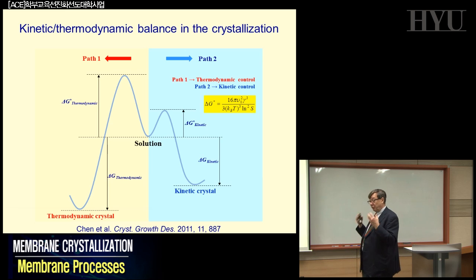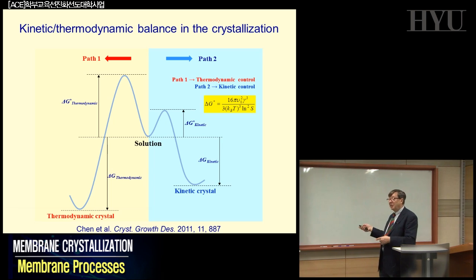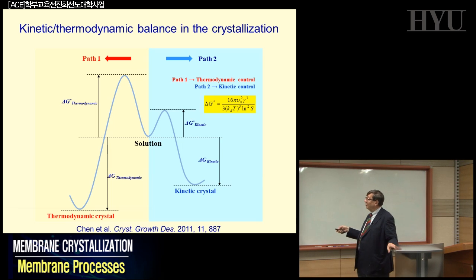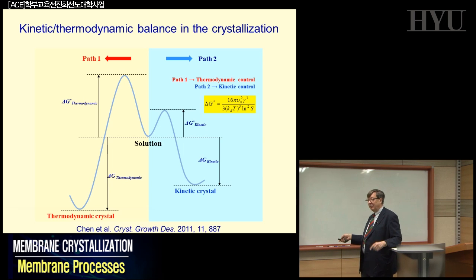So you are introducing a strong variation in the mechanism of formation of the final product, because you are able to control all that happens in the very early step of your metastable heterogeneous nucleation phase. Okay? So if you do this, you can start to calculate and to see if your prediction is valid or not, not on the thermodynamic, but on the kinetic crystals. And so the ones that we are forming and controlling in our conditions result from an acceleration of the kinetic crystals that we remove from the system, so we have a final formation of compounds that in the traditional system we are not able to obtain, as it arrives at the thermodynamically stable phase.